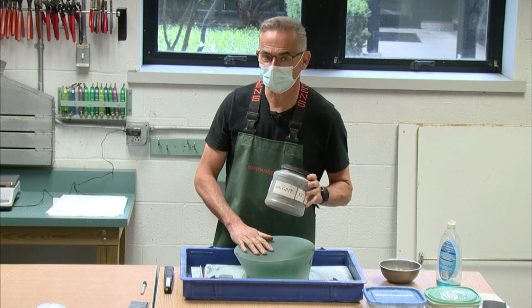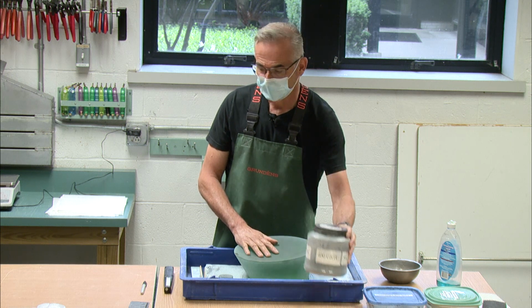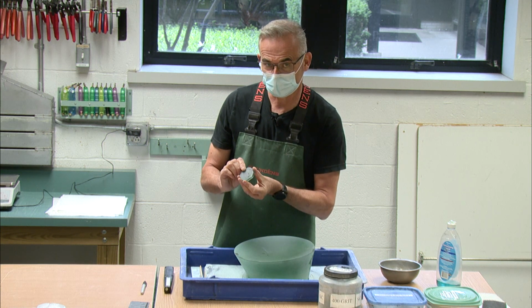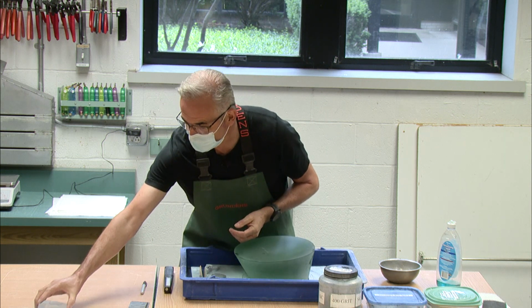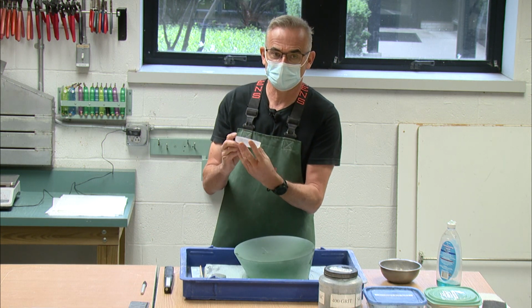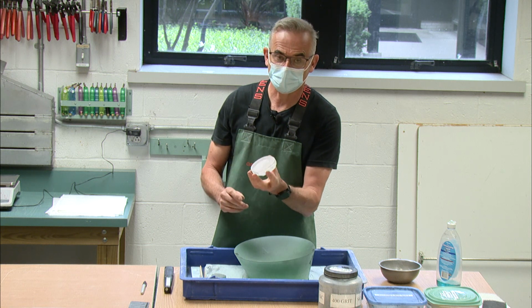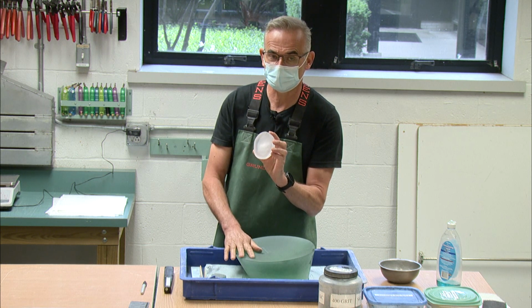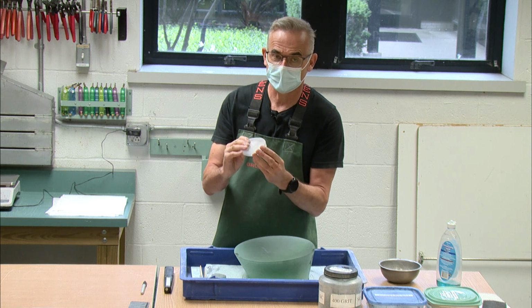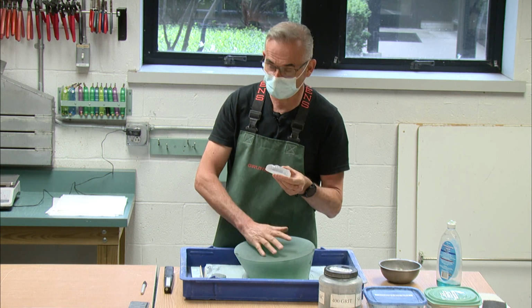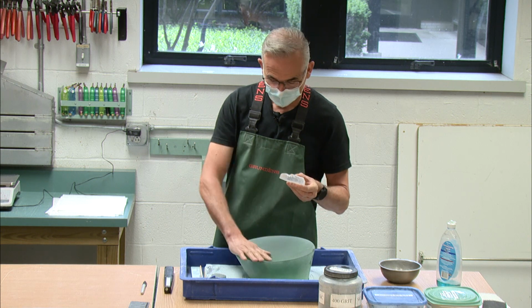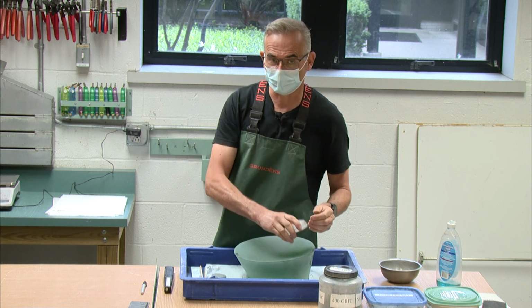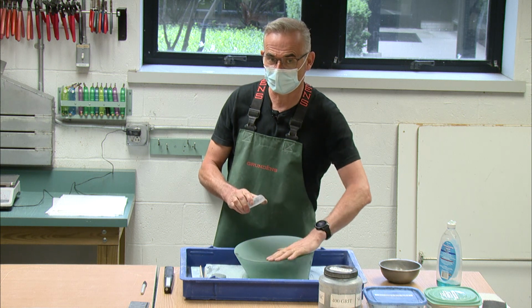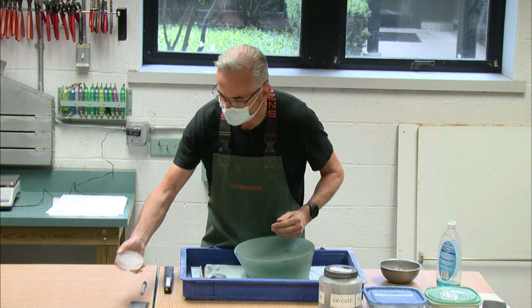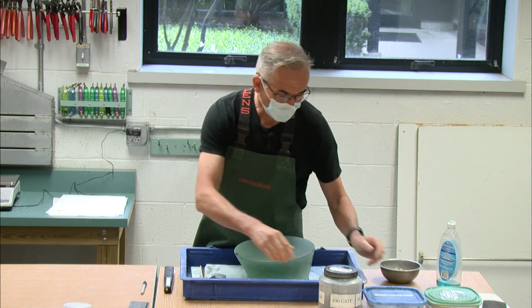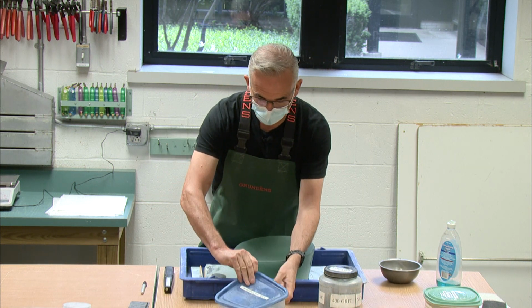And when I started on it, I was using 80 grit, and I was using a larger piece of glass. This is a little bit small. I was just using this offcut, this large slab of offcut glass. It's actually a softer glass than this. This is a lead glass, and the nice thing about that is that it conforms to this shape very, very quickly. You know, after about 20 minutes of grinding, this shape and this shape marry together very nicely. But I've gone through that process, and what I want to do now is take some of the 400 grit